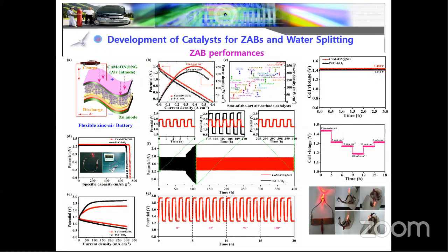For water splitting, you are using a manganese-based material. Are you mimicking photosynthesis for water splitting? Is your catalyst designed based on photosynthesis? No, my material synthesis is by the hydrothermal method. I just mixed manganese and nickel as a basic source. It is not related to photosynthesis; it is only chemical synthesis by hydrothermal method.